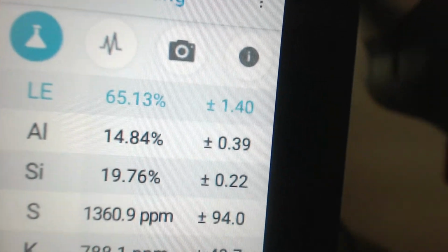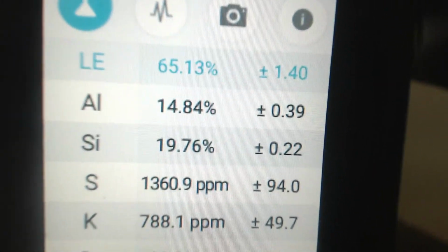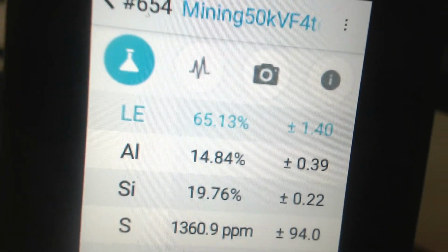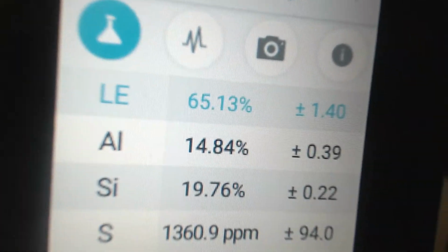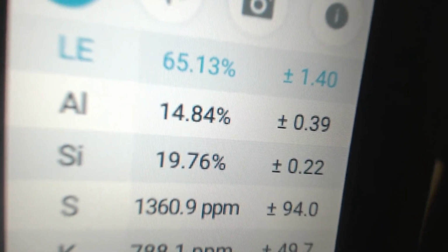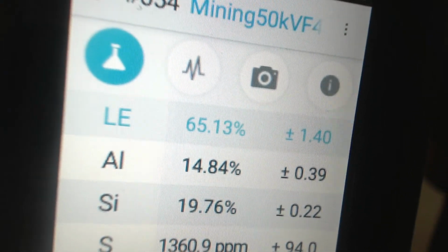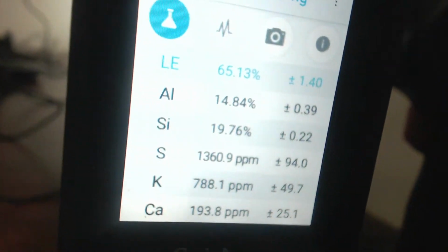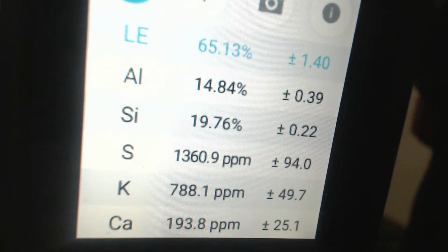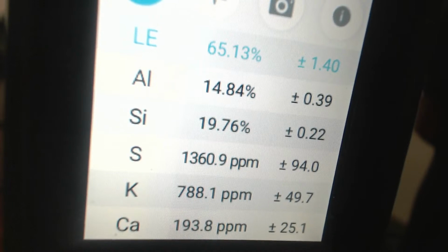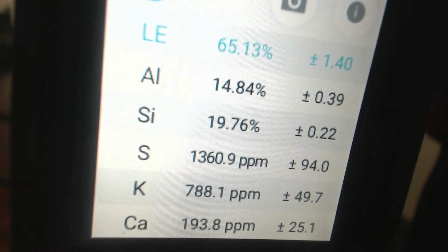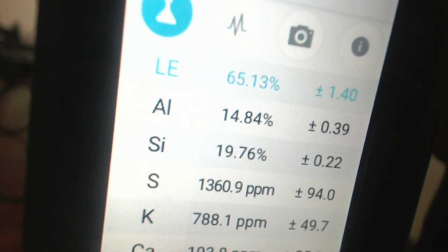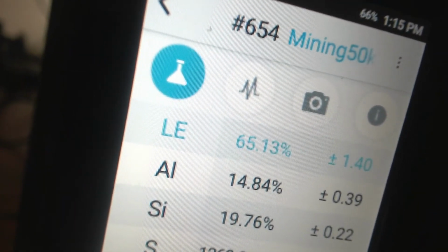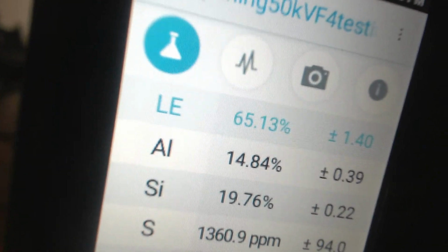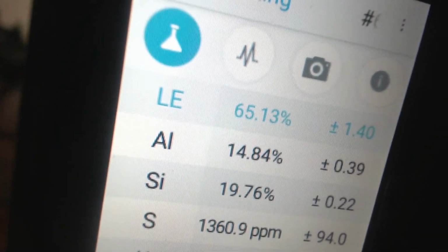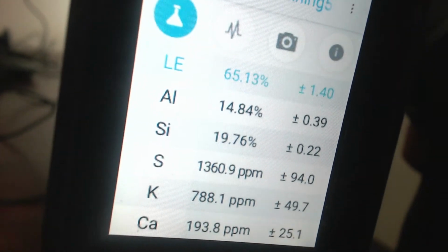So all those light elements that we cannot measure with XRF end up getting grouped together in an estimated number called LE. That's that blue number at the top of the screen. So that's representative light element, and it's our way of estimating all the light stuff that's too hard to measure directly with XRF. And the physics behind that is that as you move to lower and lower atomic number or lighter atomic mass, the X-rays that come from those elements are generally less and less energetic. So when you reach something like magnesium or sodium even, more and more of those X-rays are being absorbed by the air before they can reach your detector. So that's why we're limited with XRF. We're losing a lot of those X-rays coming from the sample to the air before we can measure them.